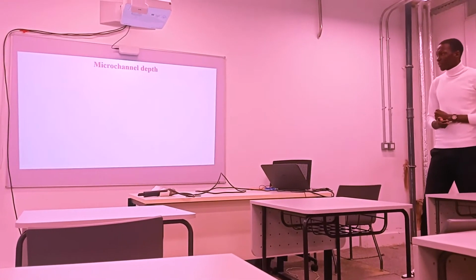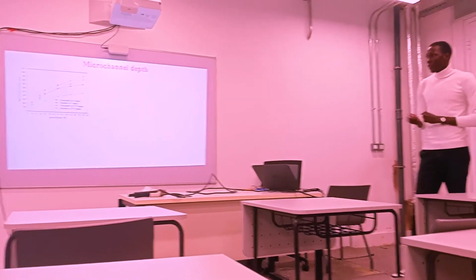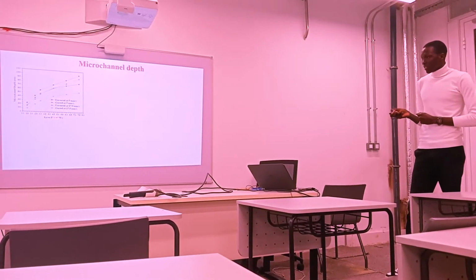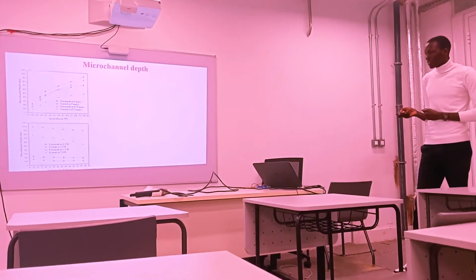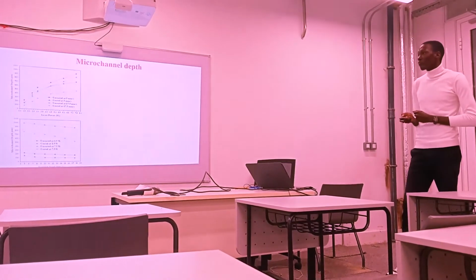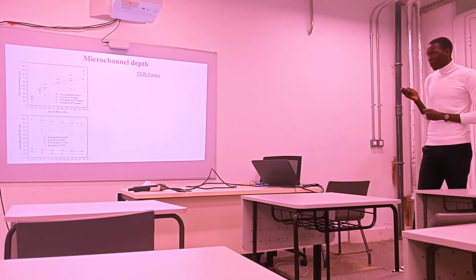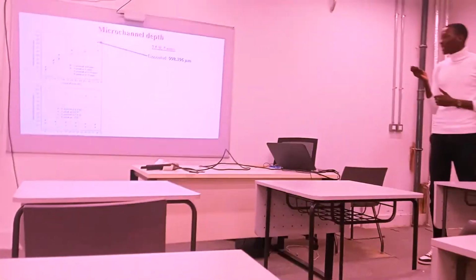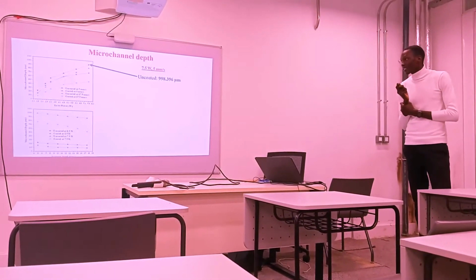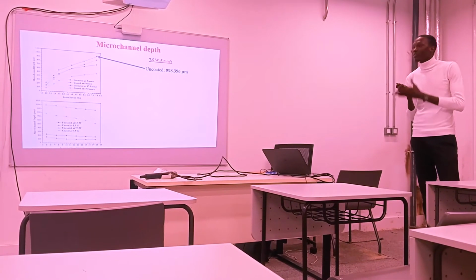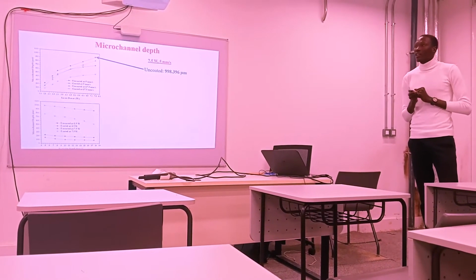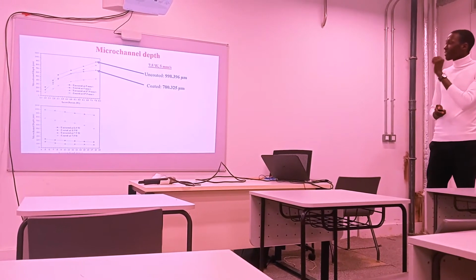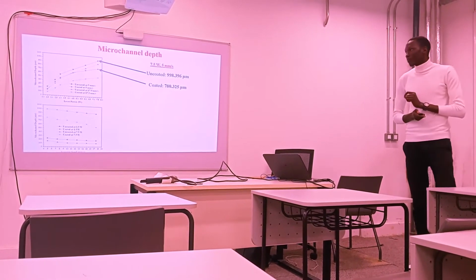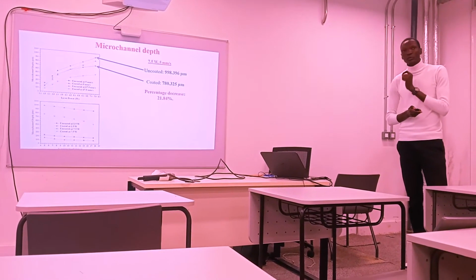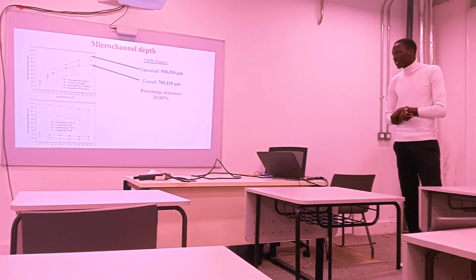Then the microchannel depth, the plot of the depth against the laser power, and then the depth against the scanning speed. Now, at the maximum power and minimum speed, we got 998.396 micrometers, microchannel depth for the uncoated. Then when we coated, we got 780.325 micrometers, a percentage decrease of 21.84%.